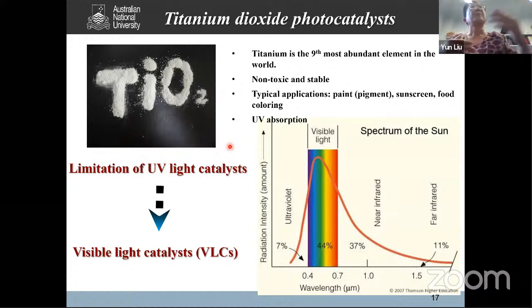Now I want to give an example to show you how this strategy will affect the photocatalyst. We know pure titanium dioxide has a band gap around 3 eV. So in that case, it is only sensitive to UV light. There is a lot of work to make this titanium dioxide work in the visible light range.